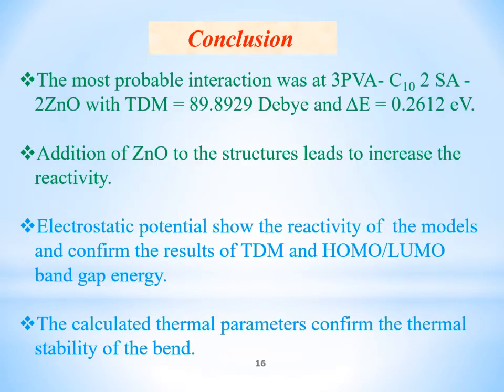Conclusion. The most probable interaction was at 3 units of PVA with carbon number 10, with 2 units of sodium alginate, with addition of 2 units of zinc oxide, and the interaction may be through the zinc atom, because the value of total dipole moment was the highest and the band gap energy was the lowest. Also, addition of zinc oxide to the structures led to increased reactivity.